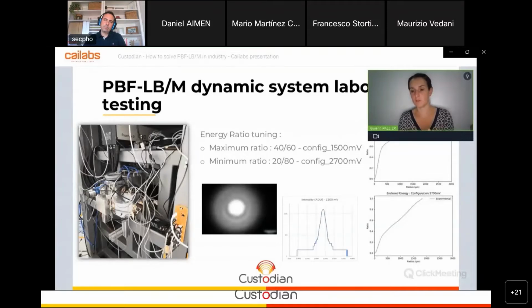For example, in 200 micron radius, you have much more power on the top compared to the bottom, meaning that you have actually much more energy inside the primary beam compared to the energy in the secondary beam. So we were very happy that we can actually tune this power ratio pretty nicely in between the targeted range.